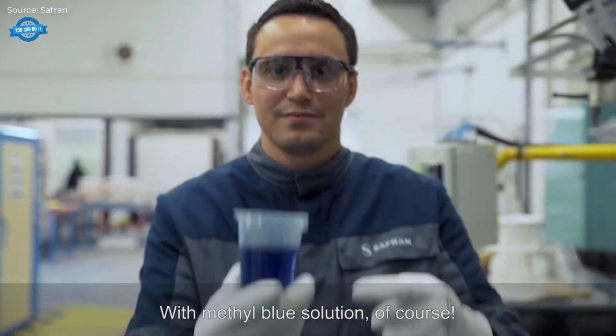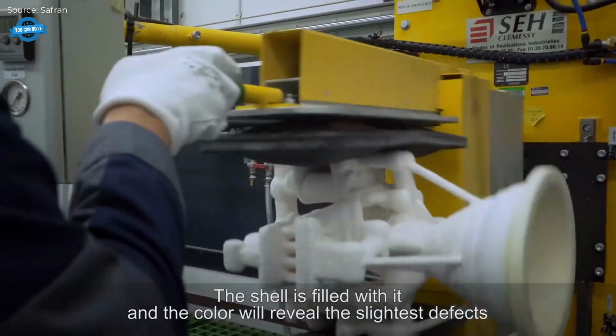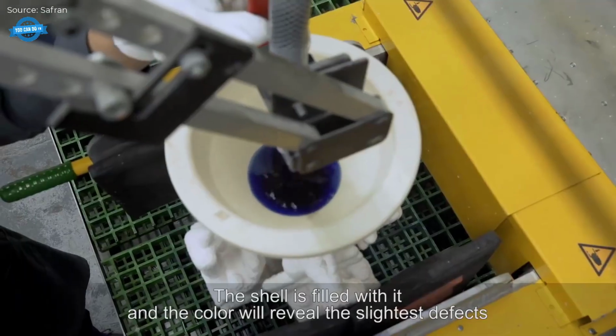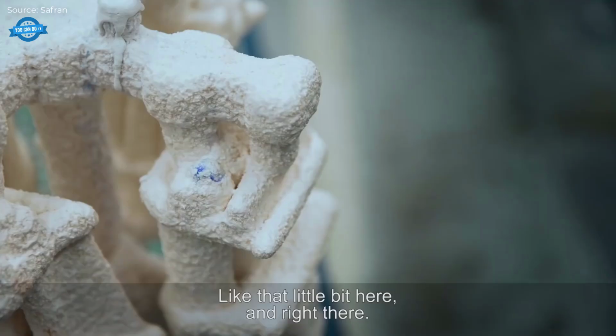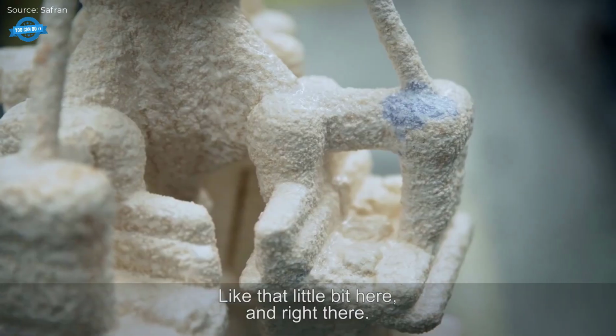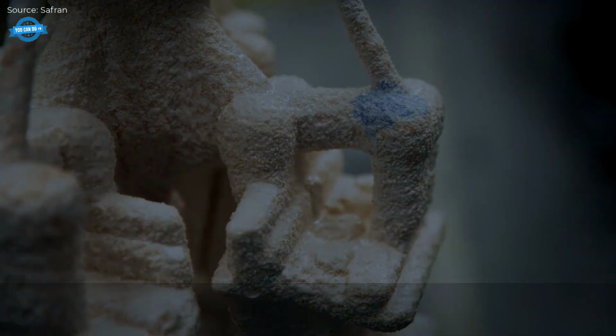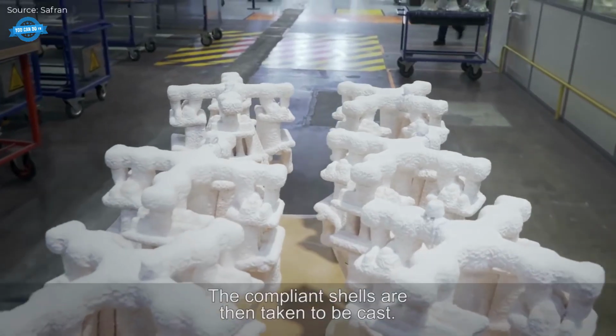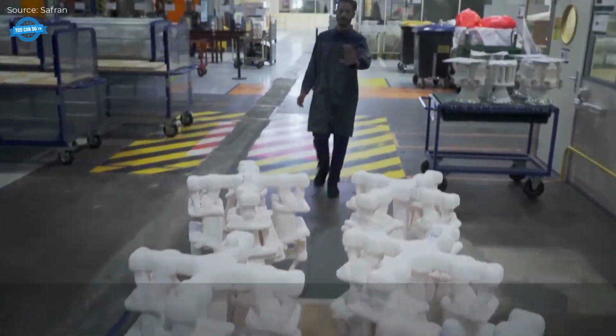Before casting, each shell undergoes additional inspections to check for impermeability. Any defect would compromise the casting process, so shells are inspected using methods like dye-penetrant testing with methyl blue solution, which reveals flaws by turning blue in defective areas.